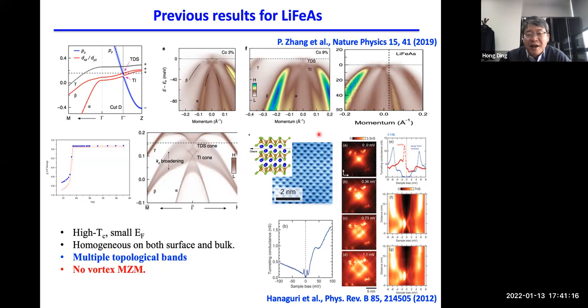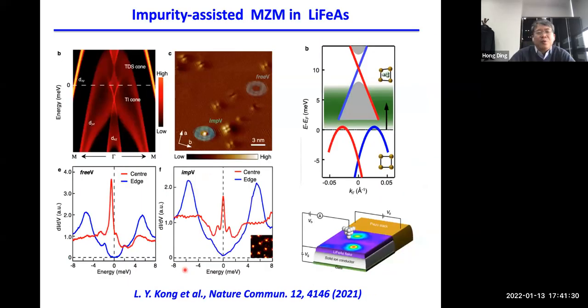Actually, one can show it's coming from this large hole, this d_xy band. So this is a big puzzle. We tried to understand why in the free vortex of lithium iron arsenic there's no Majorana zero mode. So we performed STM measurements in the free vortex. Yes, we repeat the result from Hanaguri showing this CdGM bound state away from zero.